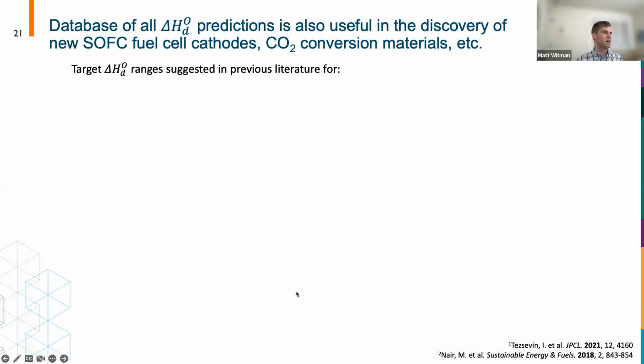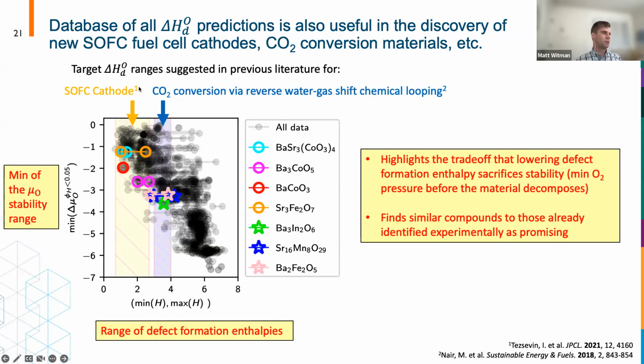So we have this database of oxygen vacancy formation enthalpies, but because people in the literature have also proposed ideal target ranges for solid oxide fuel cell cathodes or CO2 conversion via reverse water gas shift, we can quickly go through these materials and pick out ones that might be useful in these other applications.